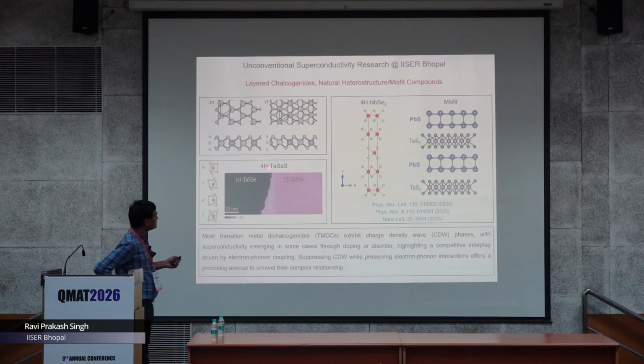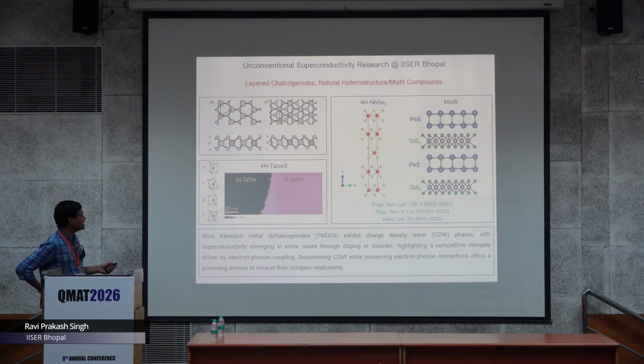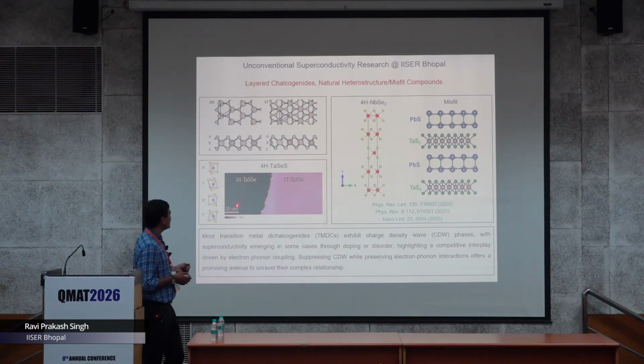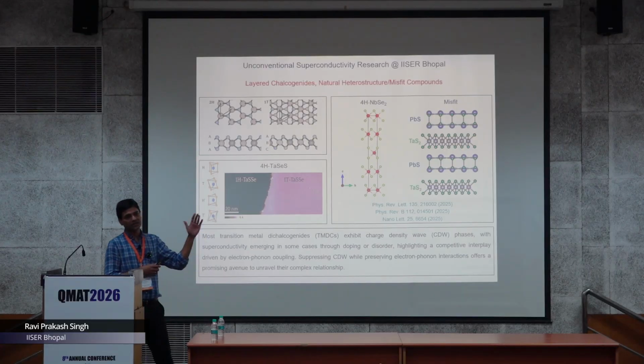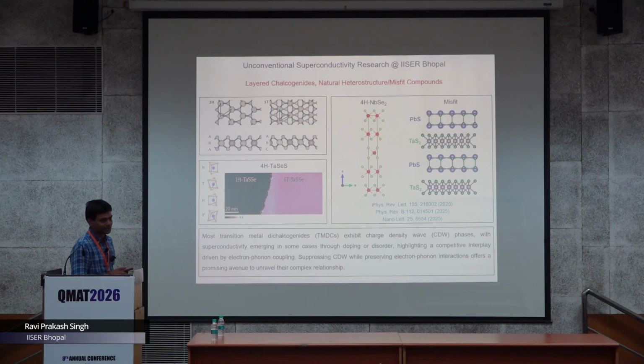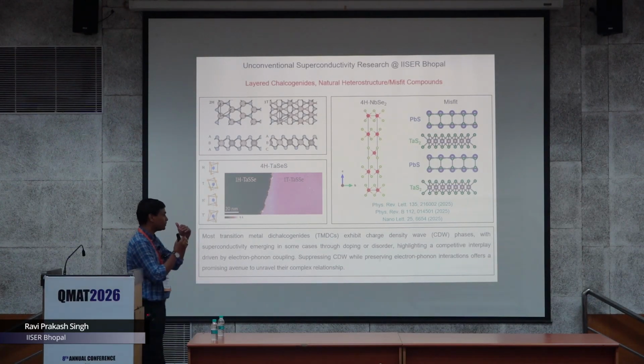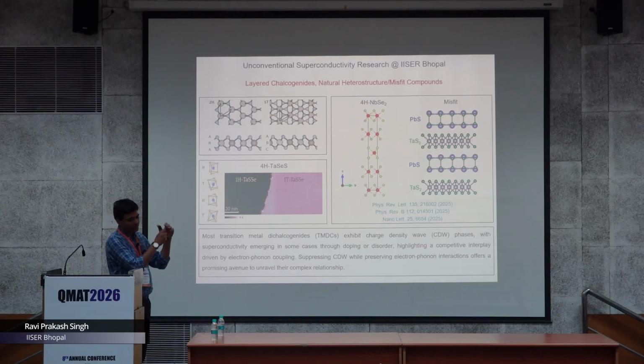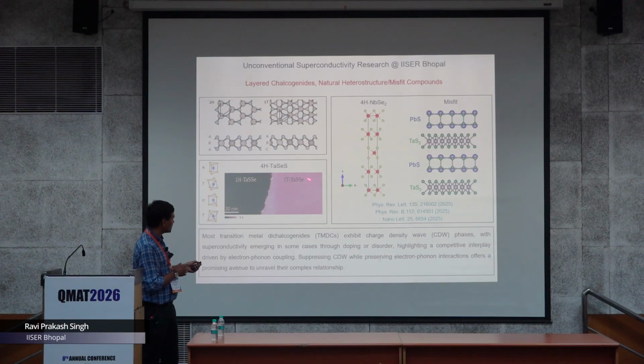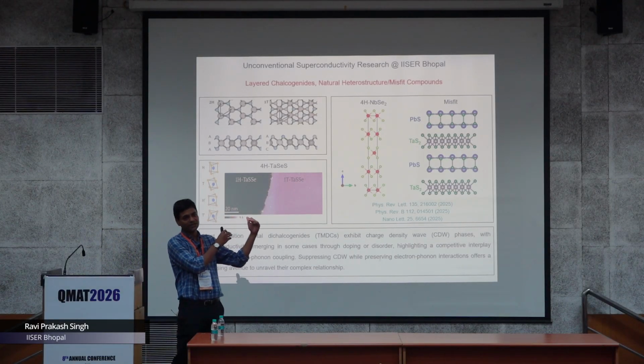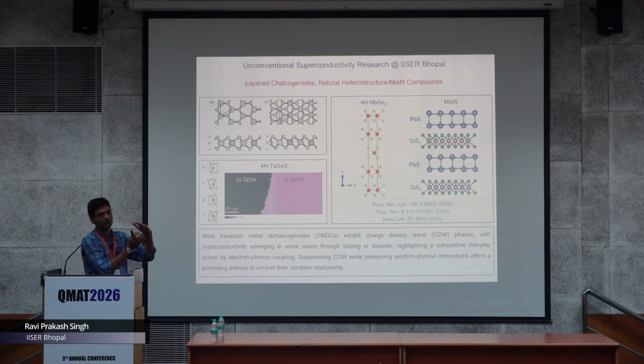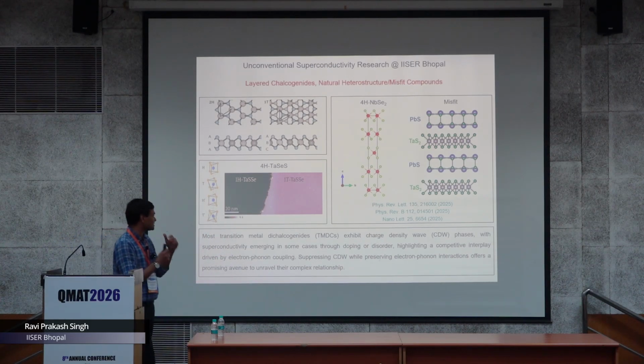So like 4H, this is a system. If you look at the 4H tantalum S2, it has a 1H layer and a 1T layer. One is superconducting, another is non-superconducting. But simply by doping the sulfur, we make both the layers superconducting, and this is a kind of superconductor where you can get two different superconducting parameters in one bulk crystal.